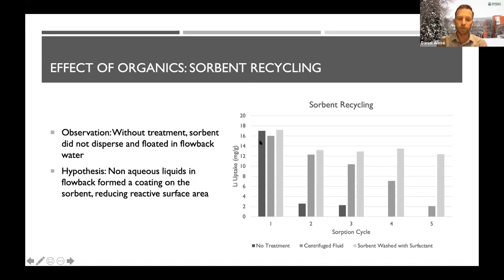So the dark gray bars here, this is cycle testing. So this is the first extraction. And then remember, I said we're going to kick it back into the cycle. So we use it a second time, a third time, fourth, and fifth, just to see, at least initially in the first 5 cycles, what was going on. And what you see, if there's no treatment of the brine, besides again the centrifugation and pouring off the hydrocarbons, is that, yeah, you get good recovery in the first cycle. That's about 17 milligrams per gram in this case, but it's radically reduced in the second and third cycle. Basically, it's not useful anymore after the fourth or fifth cycle. So say, okay, that's a problem. What are we gonna do about it?